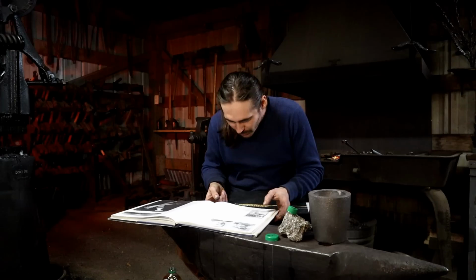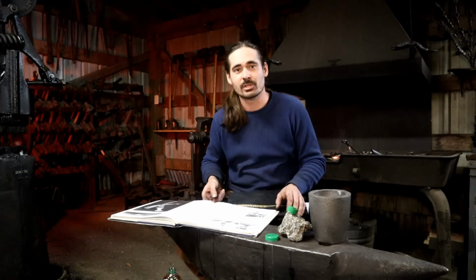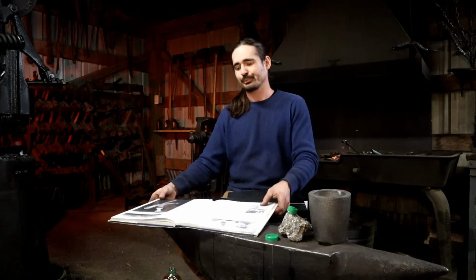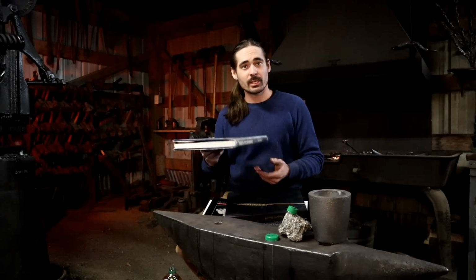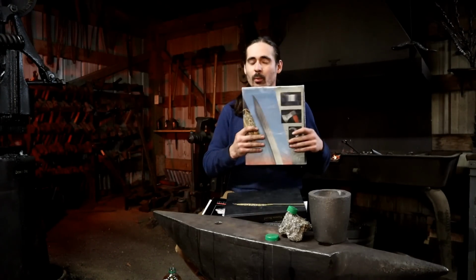So what it means is that the crucible steel has very bad properties as a steel to begin with. It is not very friendly to heat treating, and therefore when you're making a long blade, it is far more useful when you leave it in its annealed state than in its hardened state. And the hardness levels are equally abysmal. So that does away with crucible steel for a moment.